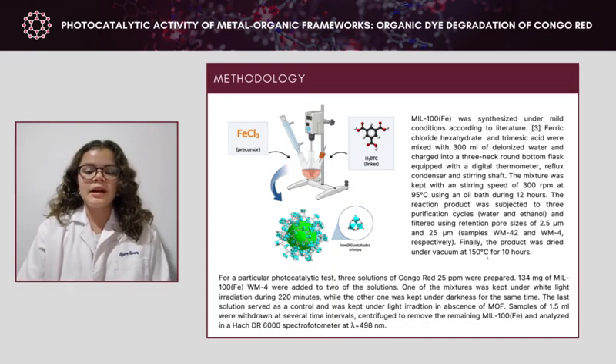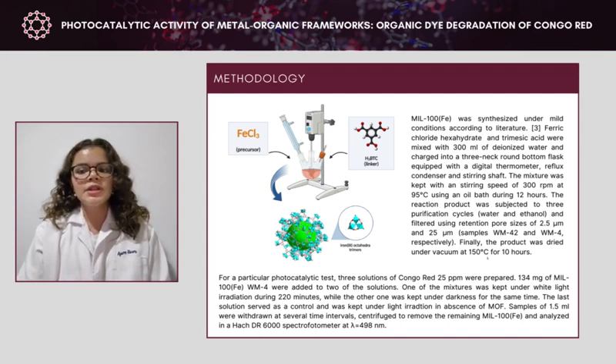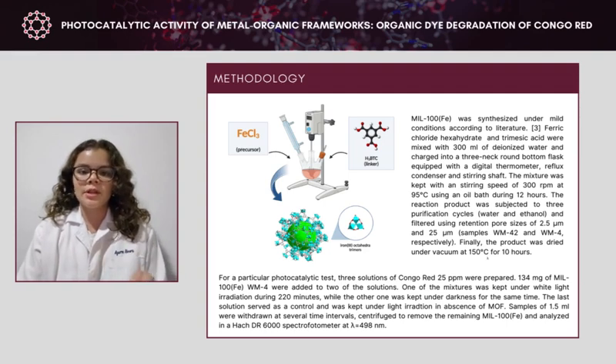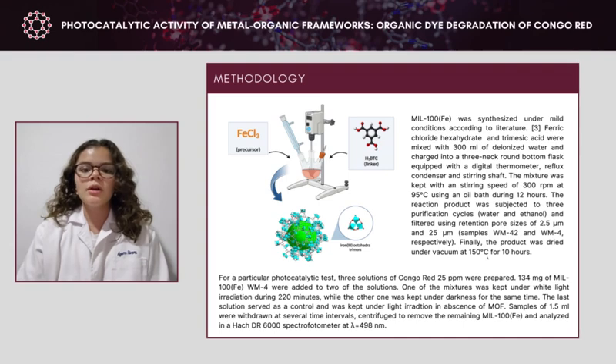As our methodology to synthesize Mesoporous iron 3 carboxylate under mild conditions, the procedure described by Sheng and co-workers was followed, making some small modifications. 6.49 grams of ferric chloride hexahydrate and 7.57 grams of trimesic acid were mixed with 300 milliliters of deionized water and charged into a 3-neck round bottom flask equipped with a digital thermometer, reflux condenser, and stirring shaft. The mixture was kept at a stirring speed of 300 revolutions per minute at 95 degrees using an oil bath for 12 hours. The reaction product was subjected to 3 purification cycles with ethanol and water and filtered using retention pore sizes of 2.5 micrometers and 25 micrometers, obtaining samples WM42 and WM4 respectively. Finally, the product was dried under vacuum at 150 degrees for 10 hours.